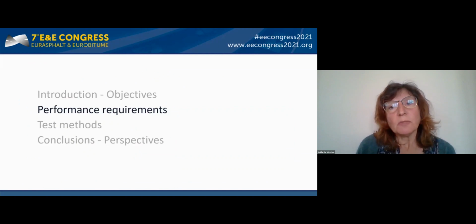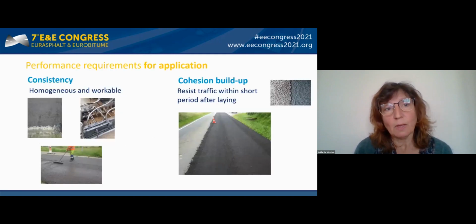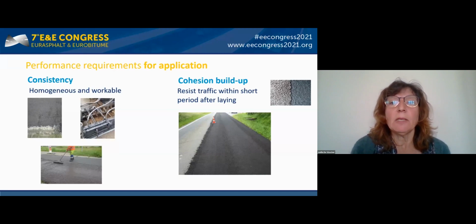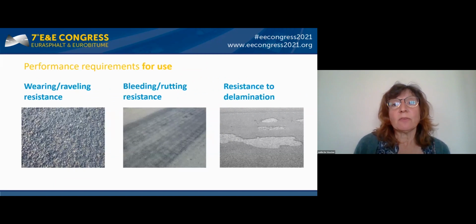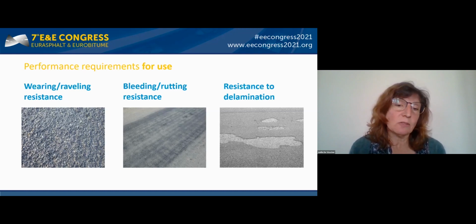But before moving to the tests, what is the performance that we require in case of slurry surfacings? First of all, quality and durability depend highly on the execution, and therefore the first requirements are a good consistency, which means that the mix is homogeneous and workable, and that you don't get any segregations or lumps in the mixture. And then also, once the mixture is applied, the cohesion of the mix shall increase rapidly to a level which is high enough to withstand the forces exerted by traffic. And then once subjected to traffic, the performance requirements are, on the left, a good resistance to wearing or raveling, resistance to bleeding, which is the phenomenon of an excess of binder appearing at the surface, and then also resistance to delamination.